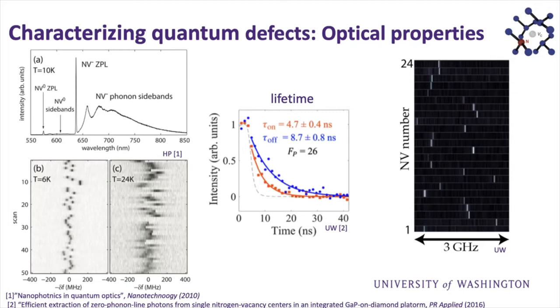And these defects are very, very good sensors. And sensing is a very exciting application of quantum defects, which I'm not going into today, but essentially if you have a very, very good qubit, very often you have a very, very good sensor. If we increase the temperature here, you can see that each one of these broadens out. This is due to phonon interactions. And for this particular defect, we know that we need to work at less than 10 Kelvin or so.